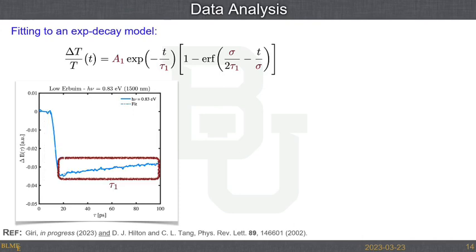In terms of the materials parameters that I get out of all of this, the amplitude here tells me basically how many carriers I've been able to create. So it'll tell me how efficient I am at creating mobile electrons in this material. This sigma here, this pulse width here, that's an instrument response of my system. That's a limit to how fast I can measure something here, because it's a limit to how fast I can dump the energy into the system.